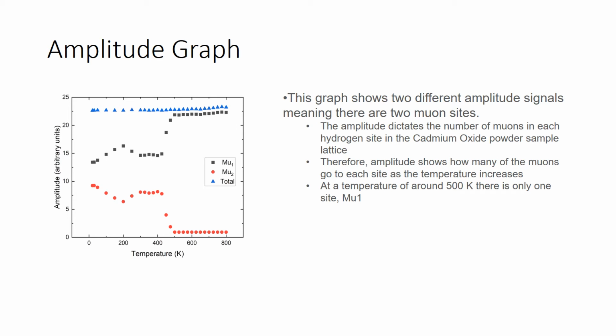As seen by the fit which I found, this graph shows that there are two different amplitude signals, or two different muon sites or hydrogen sites within the cadmium oxide powder lattice. Therefore, the amplitude shows how many muons go to each site as the temperature increases. So in my specific fit of this cadmium oxide data, as the temperature increased, the muons seem to all go to one specific site, which was mu1, as seen here by the mu1 signal.